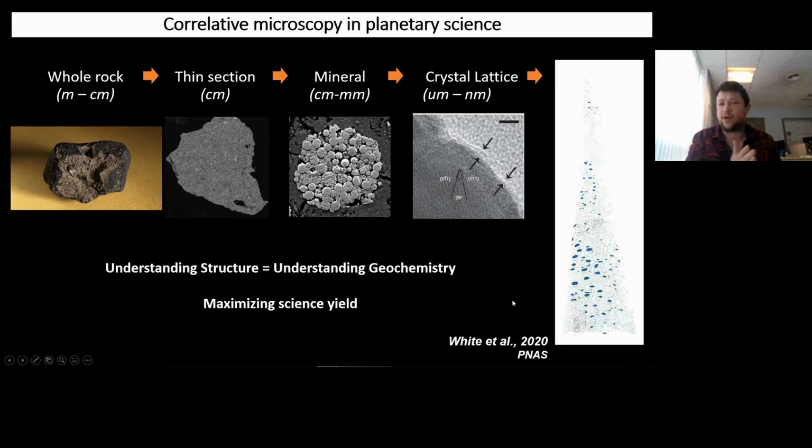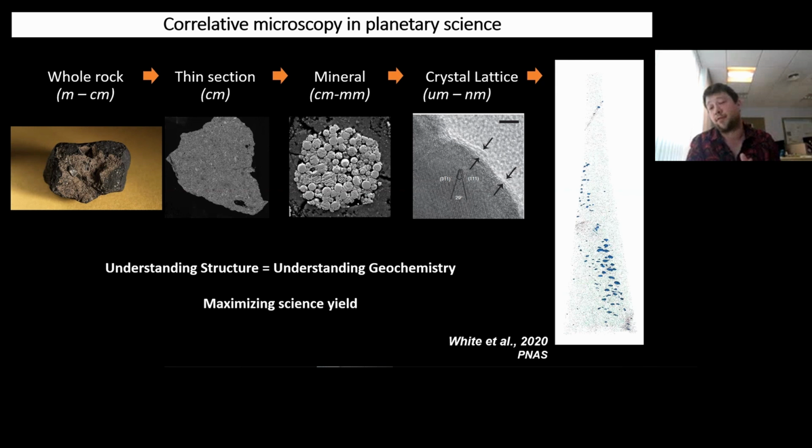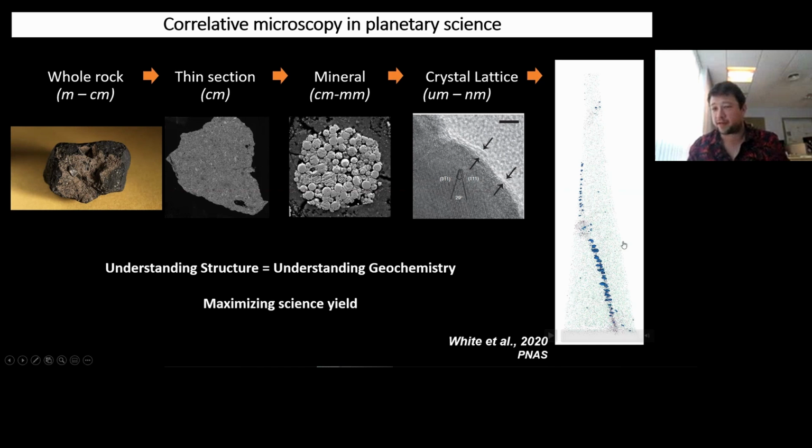It's quite nice having a video work when you share a slide rather than upload it. So here you're looking at individual atoms of iron, and in the case of the blue, individual clusters of sodium. So we can actually map out grain boundaries. You can see here, this is a 10 nanometer grain boundary running through a magnetite crystal. And that's something we can only do with atom probe at the moment for that 3D resolution.